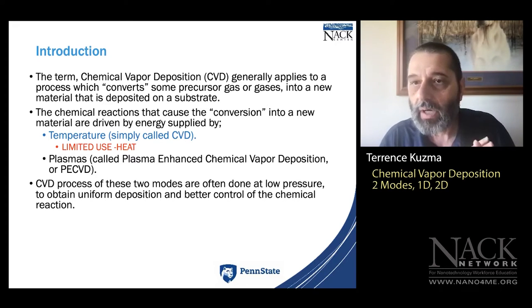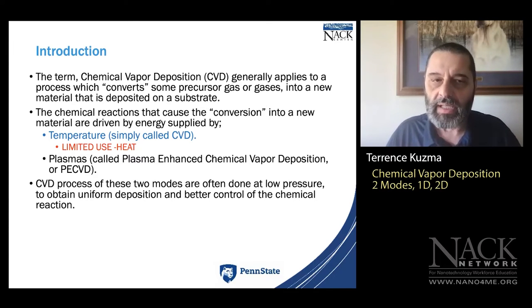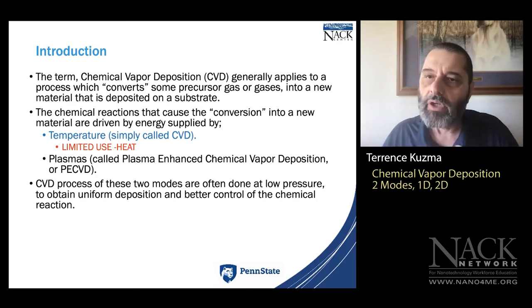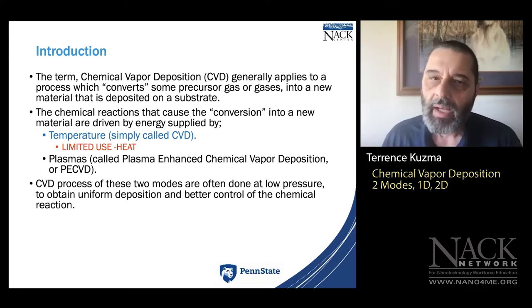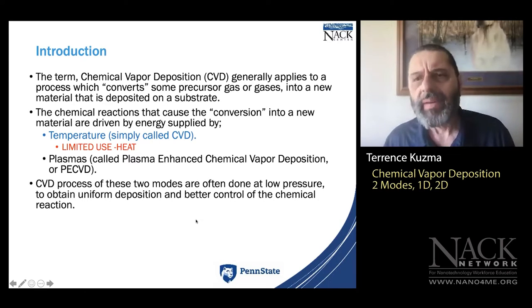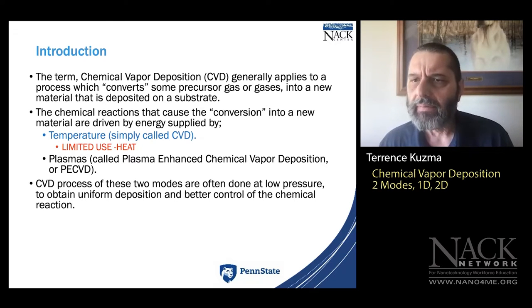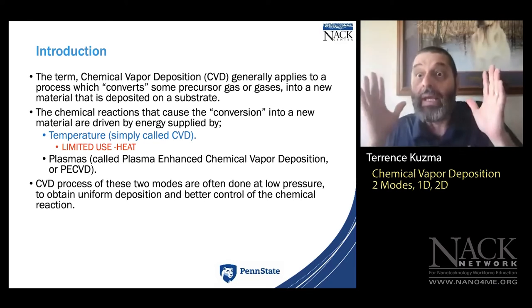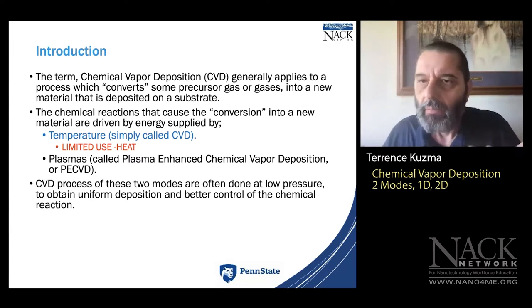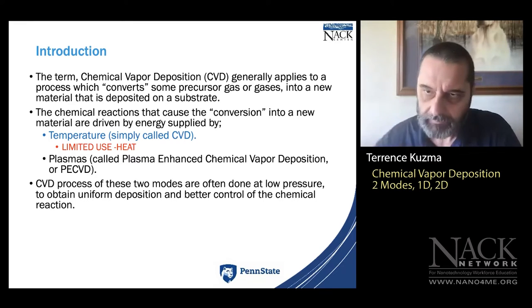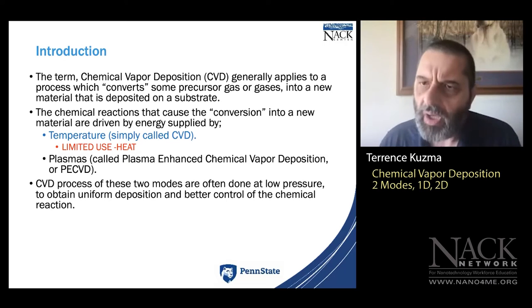The system we're specifically looking at converts gas into solid, driven by temperature. A challenge in red on my presentation: people want to deposit on flexible substrates and plastics. CVD's high temperature is the white elephant — if you coat a plastic car headlight lens at 400°C, it would melt. That's where PECVD comes in.